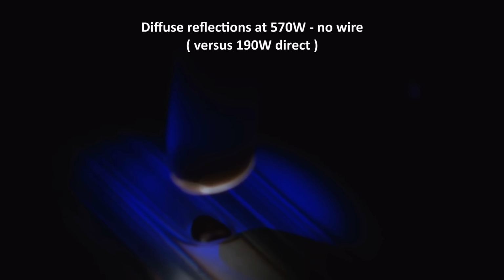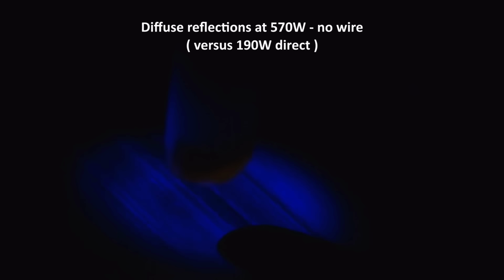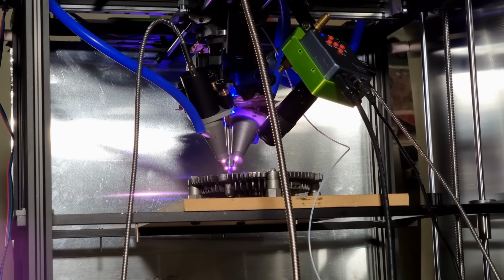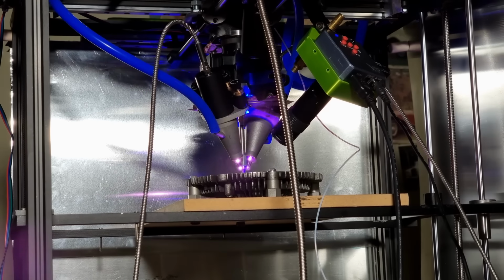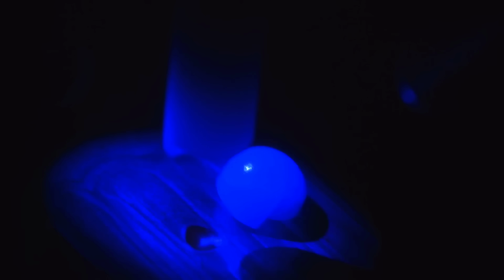I figured I might be able to sleeve it with a copper syringe if I could find one, and tested it again while observing how the lasers interacted with the weld pool. That also did not go well. In fact, from what I observed during these trials, I came to the conclusion that this whole concept might not be worth pursuing. Even though this run illustrates the weld pool with 3 beams applied, you can see how the reflections are heavily influenced by the flow of heat, leading the reflections to follow in the direction of motion. This really steers the process towards needing a higher volume of material to help keep the reflections away from the feedstock, and that was a compromise I was unwilling to make.